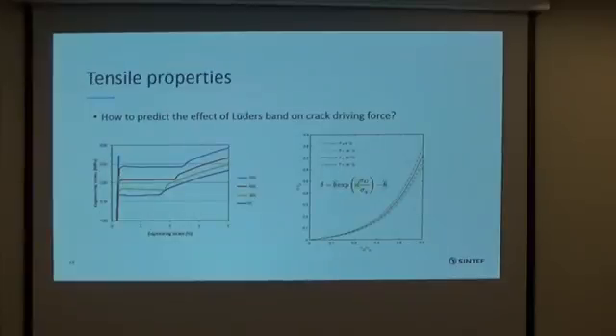The next issue is tensile properties. If you test your material from room temperature to low temperature, this is the typical curve you will get. With a decrease of temperature, the yield stress will increase, and one very special issue is the Lüders band. You will have an increase in Lüders strain in your material properties. How we understand the effect of such material properties on crack driving force is an important issue. Recently we proposed a model to understand this. Using the proposed model, you can simply predict the crack driving force using data from testing.